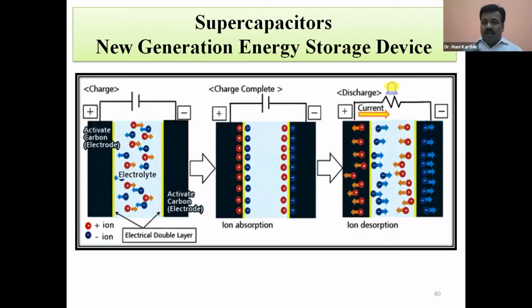Then we are using different types of electrolytes. The electrolyte determines your voltage. If you take aqueous-based electrolytes, for example KOH, potassium hydroxide, 6 molar KOH or 1 molar sulfuric acid are the well-known electrolytes. These electrolytes are dissolved in water, because they are aqueous-based electrolytes. What is the problem? The electrochemical potential window of water is 1.23 volt. Above 1.2, water can split into hydrogen and oxygen, so the electrolyte is not suitable above that because you get electrolysis. So the window of aqueous electrolyte is limited. We can go for a maximum of 1 or 1.1 volt.